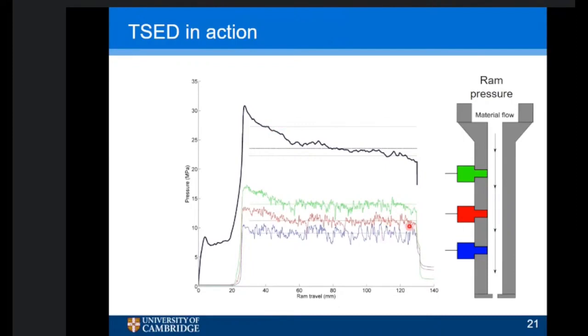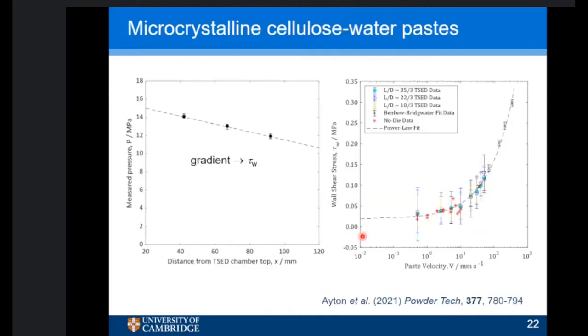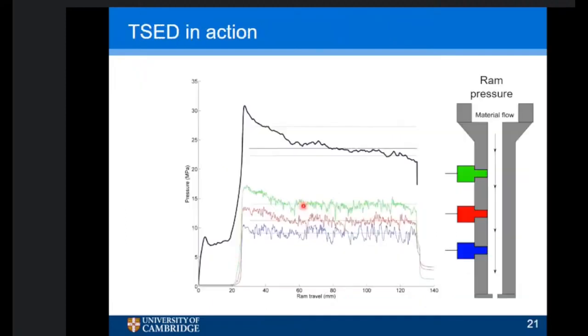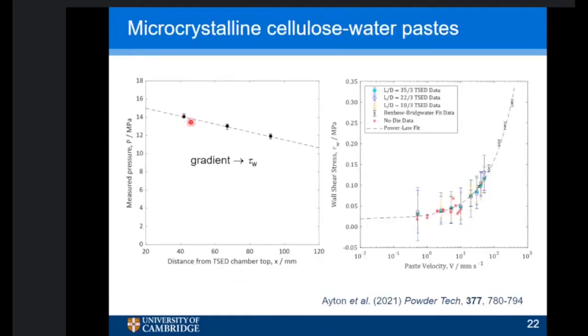These are the local measurements of the normal stress. And as you can see, they lie in the right order. And what we can do is plot those against position, and then we will get an idea of what the wall shear stress is. So that's the concept. And here's some results for the measured pressure against the distance from the TSED chamber. So that distance is effectively the distance from up here, the distance along the die. And you can see, oh, look, they look quite straight. So that's quite nice. And from the gradient, we get the wall shear stress.